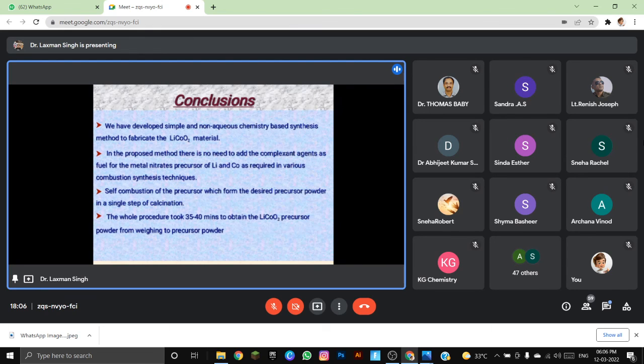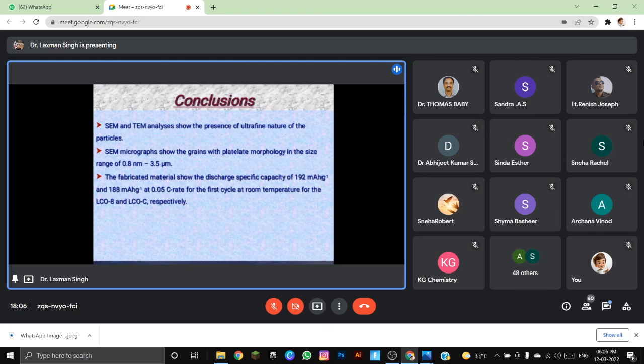In conclusion, we have developed a new method, flame synthesis, to synthesize lithium cobalt oxide for lowering the cost of lithium ion batteries. In the proposed method, we are not using any complexing agent or fuel such as glycine, urea, and others. We just mix the lithium and cobalt precursors, and synthesize the material within 35-40 minutes, with combustion of the precursor and single step calcination, and the whole process takes 35 to 40 minutes.